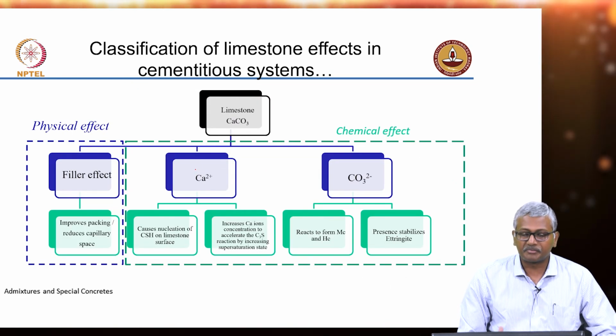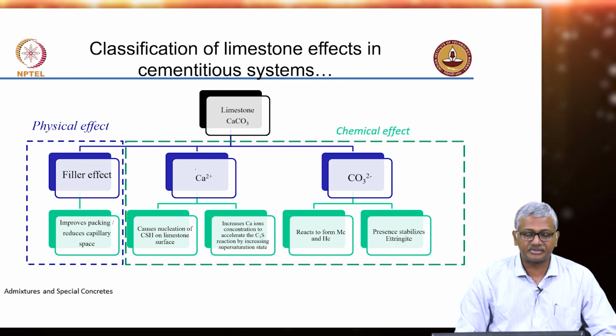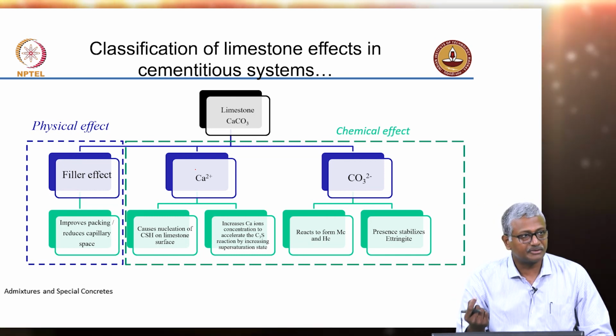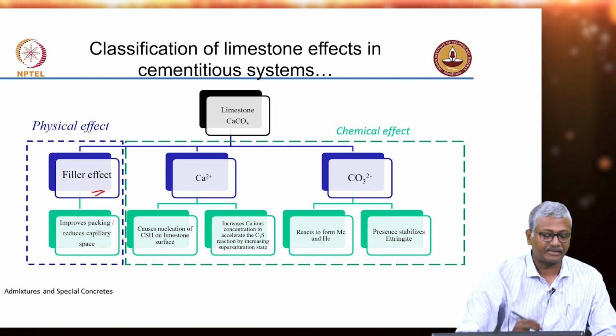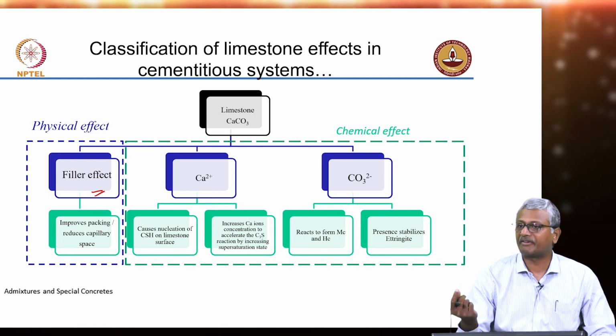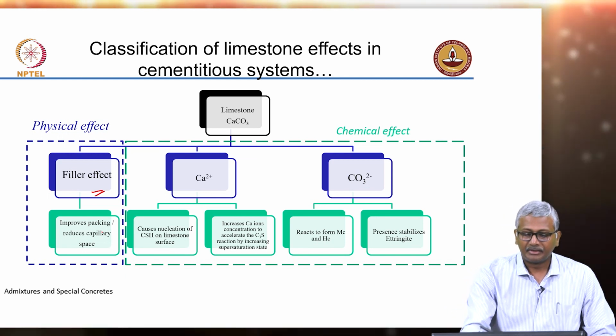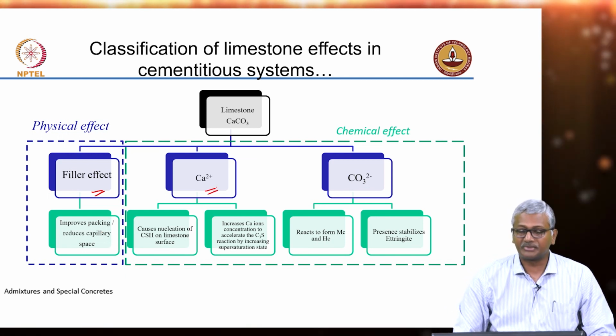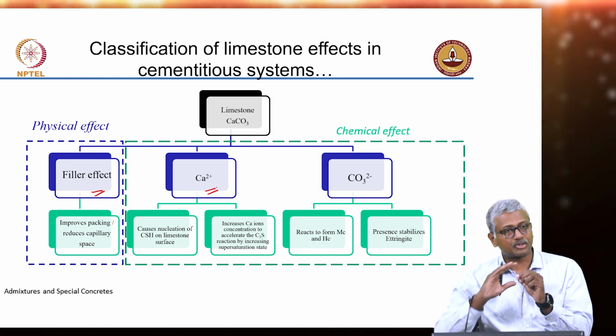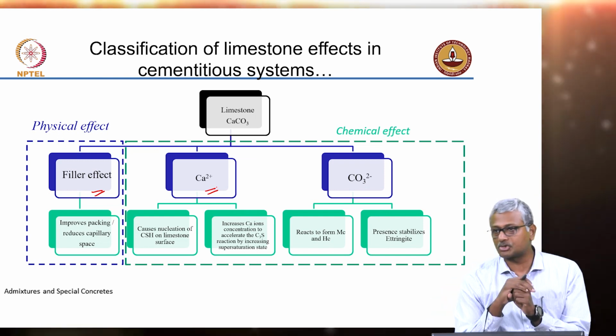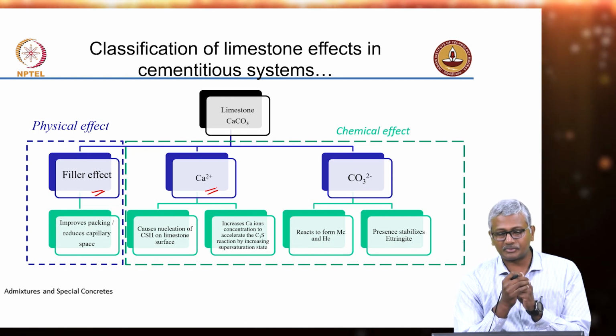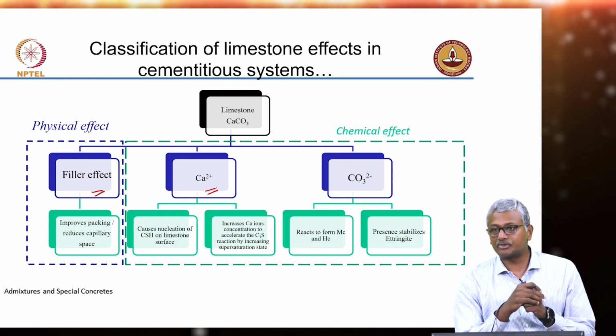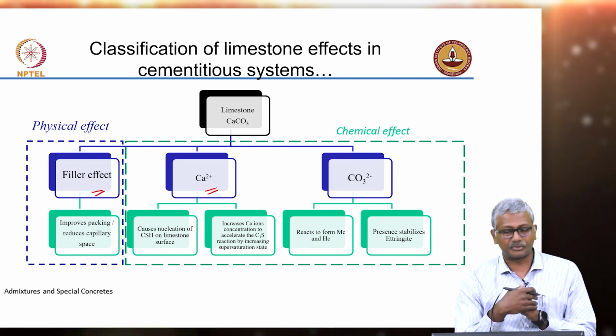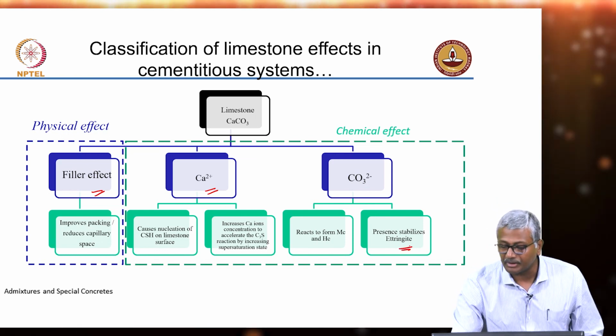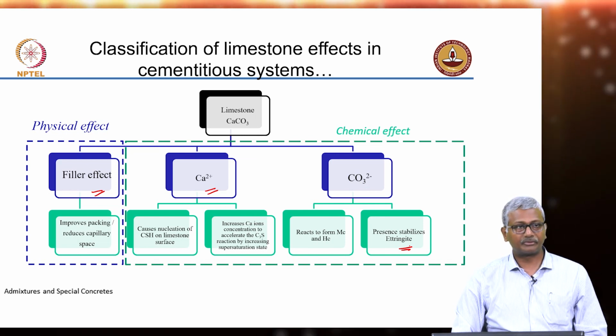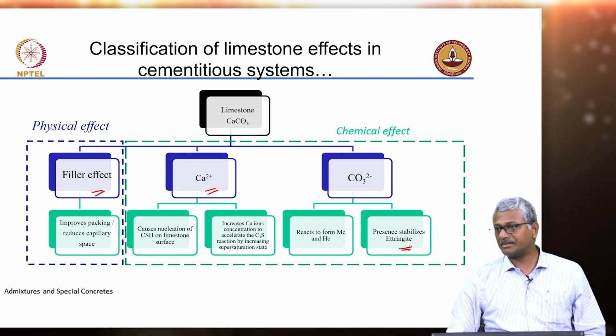So, just to put this in perspective, if you have limestone effects in cementitious systems, limestone is a fine filler. So, it will obviously have a filler effect, it will improve packing and reduce capillary space just by the fact that it's a fine material. Because limestone gives calcium, the surfaces, we discussed this earlier, that fine particles offer a chance of nucleation of CSH on the surfaces, and that's what's happening with limestone. The carbonate reacts to form monocarbonate and hemicarbonate. So, additional hydration products form and your ettringite gets stabilized. So, limestone has a real beneficial effect in cementitious systems.